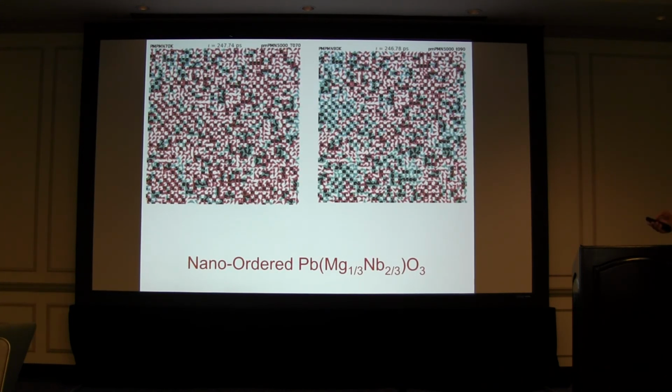This is at a temperature down in the relaxor region, and the black and white squares underneath represent the chemical order. So when you see a nice chessboardy kind of arrangement of black and white squares, as you see here, that's a chemically ordered region. The red and blue arrows represent the Z components of the local mode variables.